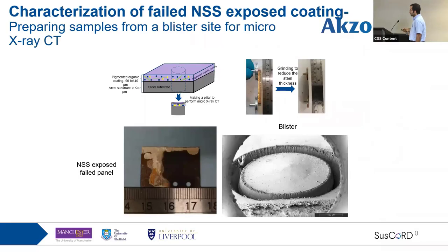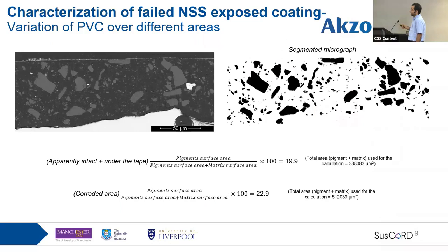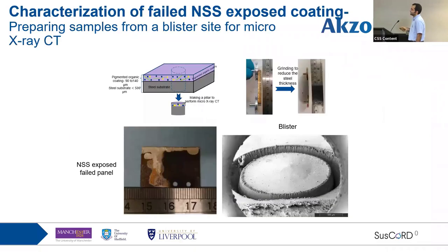So our hypothesis here was, the evidence suggested that probably there are elongated clusters forming there. We have a lower thickness. So we decided to do an X-ray CT of a blister. In order to do that, we needed to lower the thickness of the substrate. And then we used a triple beam SEM, which has both a laser installed on the SEM and also a plasma FIB, to prepare this sample. And then we used this sample to get our X-ray CT data.